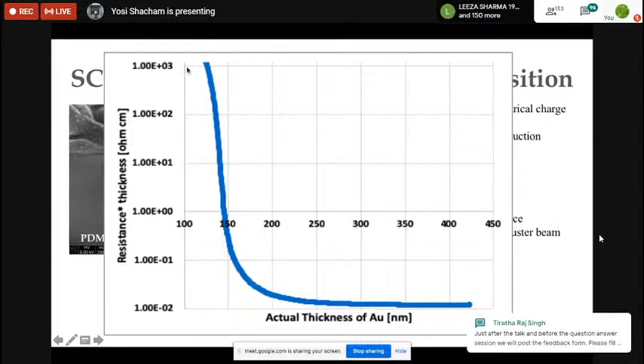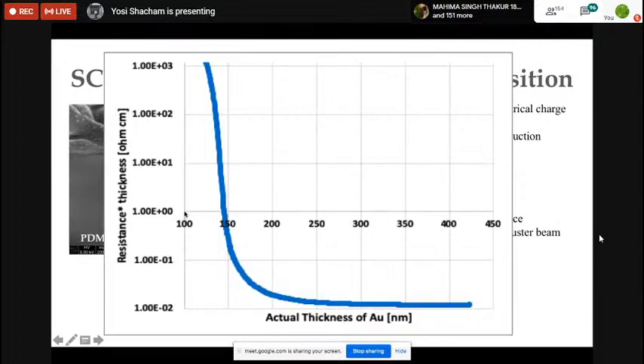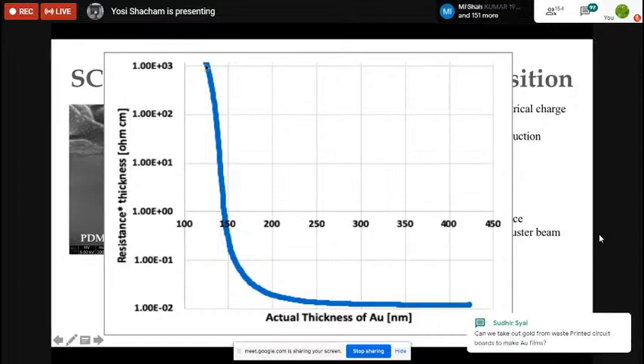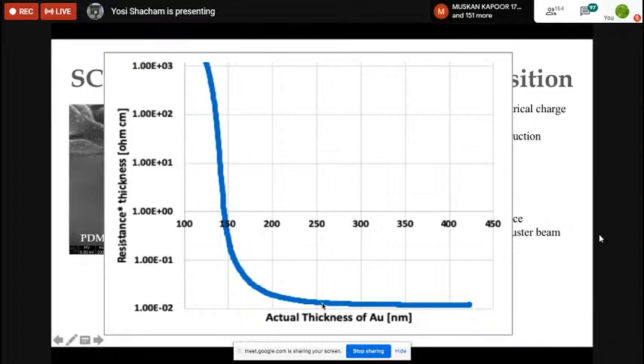This is ohm centimeter. This is very, very high. When the gold film is, this is 100 nanometer of gold. If you have less than this, the resistivity is huge. It's almost not infinite, but giga ohm and more. Above 100 nanometer, the resistivity goes down from 1 kilo ohm centimeter to 10 to the minus 2. The resistivity goes down by 5 orders of magnitude.